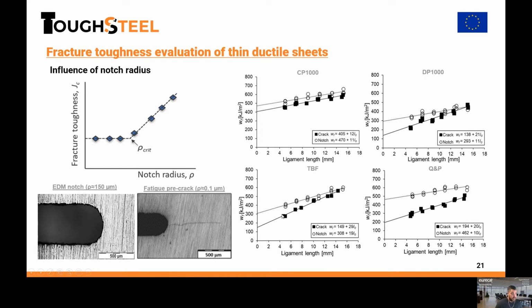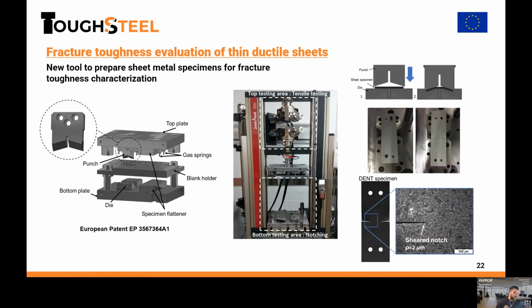There are others where the fracture toughness is drastically reduced to half of the value obtained when using notches compared to when you use cracks. And this is important to keep in mind also: if you want to measure accurate values, we need notches that are as sharp as possible, as close to the fatigue pre-crack as possible.